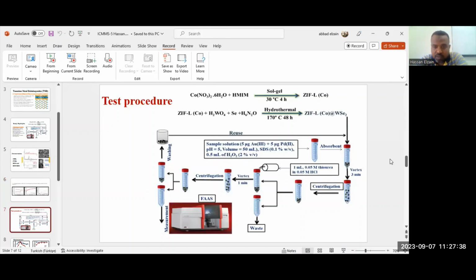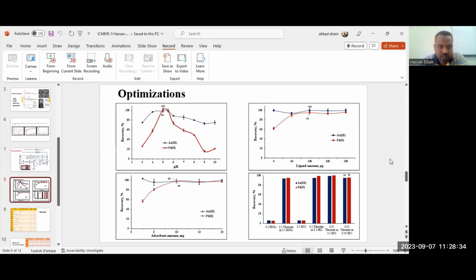The test procedure, as you've seen: we have prepared ZIF-L cobalt with the sol-gel method. Then we have covered it with tungsten selenide. We use the hydrothermal method for preparation of tungsten selenide on the surface of ZIF-L cobalt. We also have the pre-concentration method in this slide. We use little time from the beginning to the end. This is a simple method. For the optimization results, we have a lot, but we have selected the important ones, like